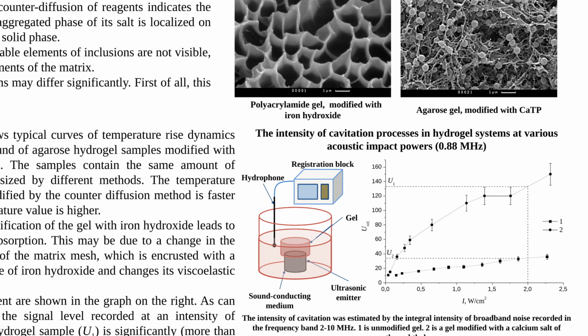The graph on the right shows the corresponding cavitation measurements. At an acoustic intensity of 2 watts per square centimetre, the signal recorded from the modified hydrogel was more than 4 times higher than the signal from the unmodified gel. This indicates that the conditions for the initiation and development of cavitation are substantially more favourable in the modified gel. The aggregates may act as generators of cavitation nuclei because of their internal structure, including movable pores, curved contacts, and the specific state of the medium within the aggregates.